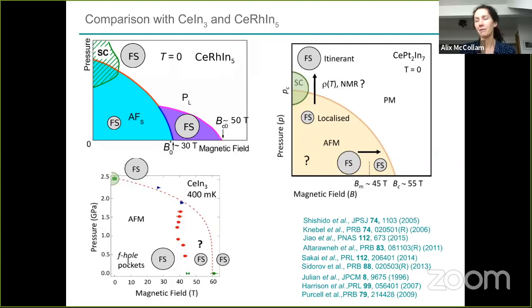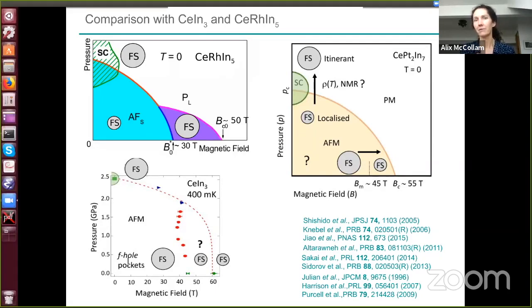They can be 10 electron masses or 7 or 6 or something like that. So the temperature dependence is still quite strong. So you don't need to be over a very wide temperature range in a specific phase to be able to measure them. Okay, so then this is cerium, platinum 2, indium 7.